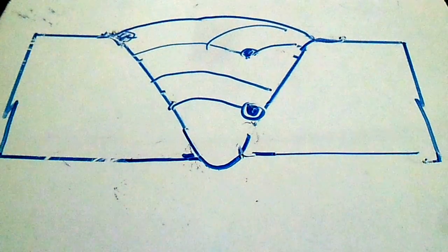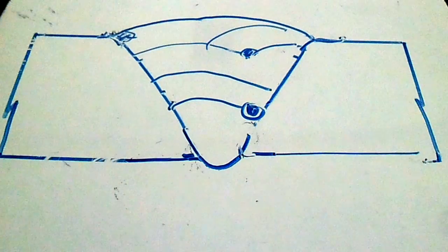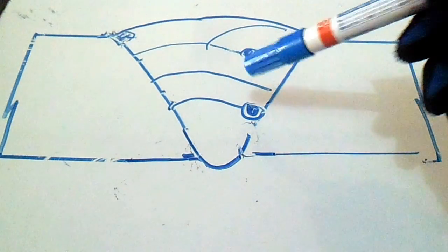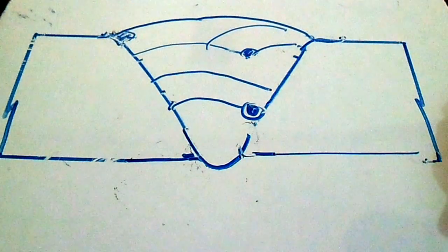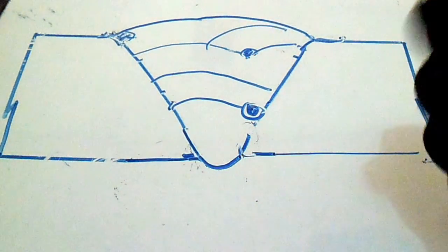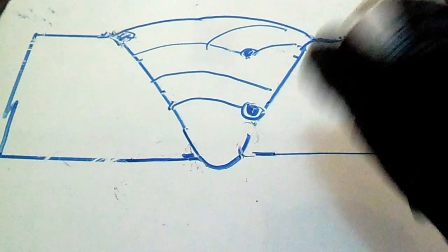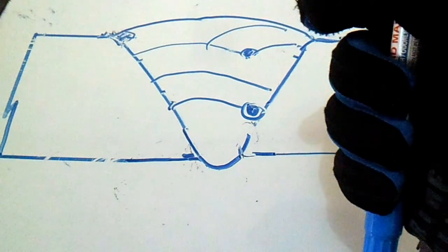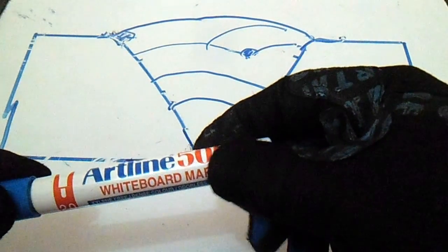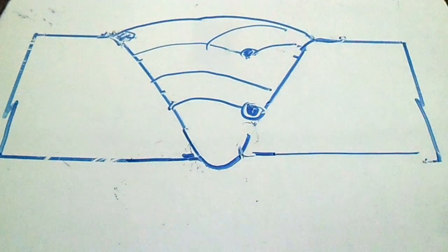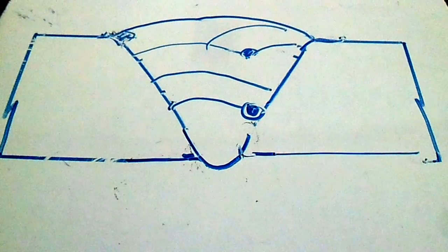so this is slag inclusion. Okay, so slag inclusion here, they have slag inclusion here, it's also slag and slag. So we have three slags. The reason why is also incorrect waving, and during root pass and hot pass, the welder is not cleaning or removing the slag. So this is slag inclusion. Okay, so next defect is,